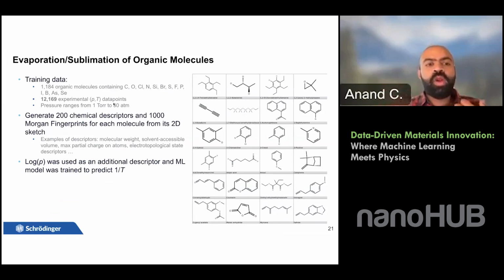The volatility of these molecules was measured at different pressures. So what was the boiling point of this molecule at a given pressure? The pressure ranges from 1 torr to 30 atmosphere, so a huge range of pressures. And this could be for a variety of different applications. For ALD and CVD, it could be at one pressure range. For volatile organic compounds, you may be interested at a lower pressure range. So we want to make a model that can predict the boiling point of these molecules at any pressure.